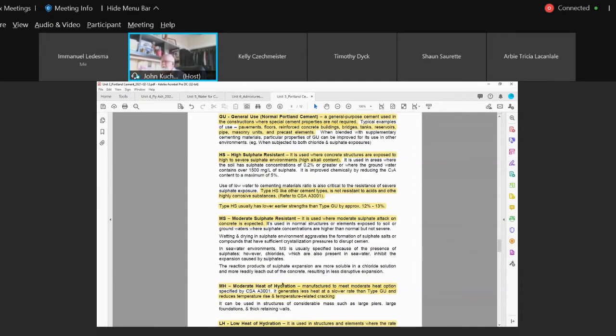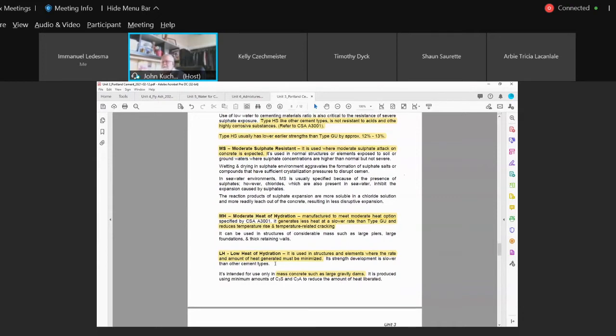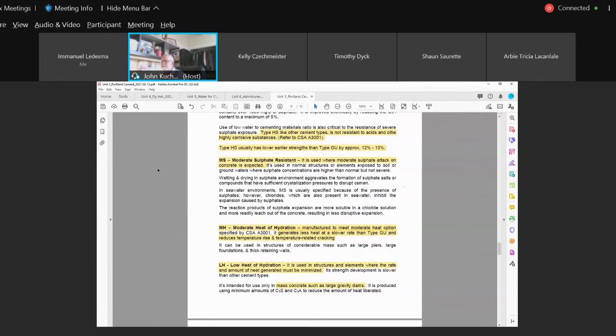So again, moderate heat of hydration, low heat of hydration, and these are areas where you have to be careful. It's also if you're involved in construction and you're pouring concrete in winter and you've heated it and you hoarded it. It's minus 40 outside, but in your hoarding you're at about 15 to 20 degrees Celsius, nice and toasty. That's where you eat your lunch, that's where you strip off your big coveralls and your big Carhartts because it's warm in there. Now keep in mind there are specifications. You just don't, after 7 days, or whatever the spec calls for, to heat and hoard, just strip that hoarding off, boom, because remember it's 20 degrees on the inside and minus 40 on the outside.